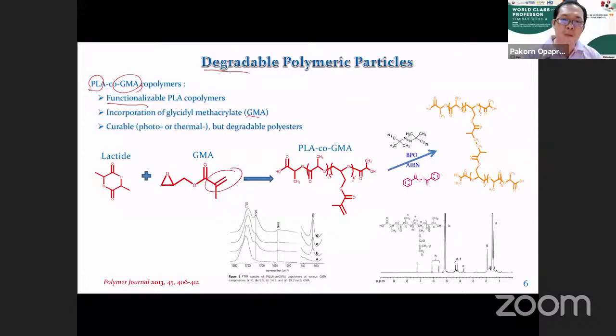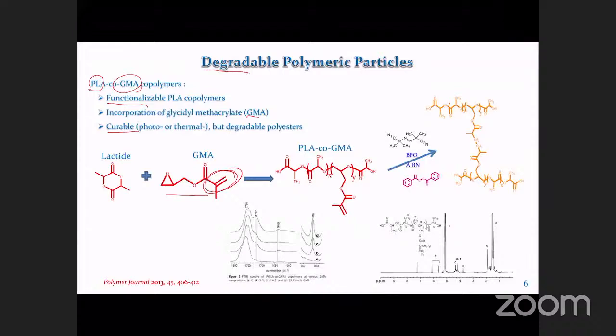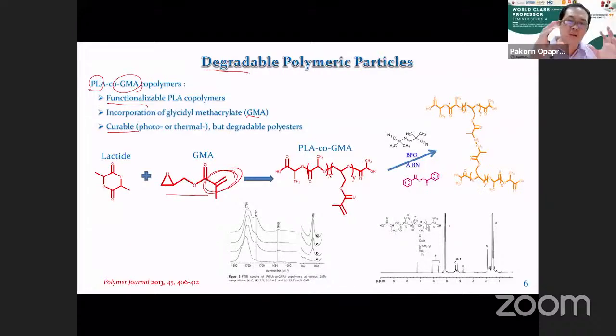We can do some further modification to the structure of these materials. And we also know that this unsaturated group is very unique for cross-linking reaction. So therefore, we can make this into a cross-linked structure, either by photo or by thermal initiator, and make them into network copolymer. However, because the base of this copolymer comes from PLA, which is degradable, we consider this a degradable network copolymer, and we synthesize this systematically.